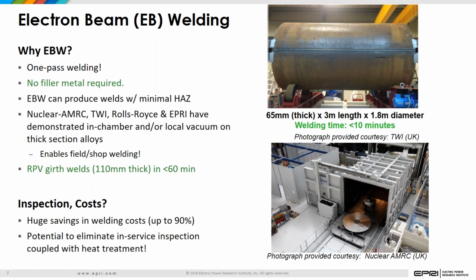That's basically 4 3/8 inch thick welds, girth welds for the reactor pressure vessel in about 60 minutes. Now, do you say, is that possible? Well, if you look at the upper right-hand side of the slide, you can see a large weld that was done in about 10 minutes. This is a 65 millimeter thick weld that's about 3 meters in length. The welding time for that was less than 10 minutes.